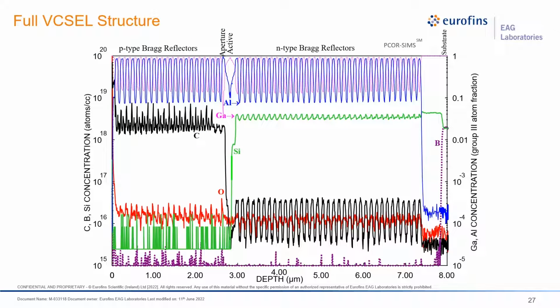This particular wafer uses a carbon-doped P-type AlGaAs DBR, a silicon-doped N-type AlGaAs DBR, and an undoped low aluminum AlGaAs active layer with a multi-quantum well. And this particular sample is one that we designed ourselves and had one of our customers fabricate for us because we could not use an example of a real customer sample that we use in our analytical service business.